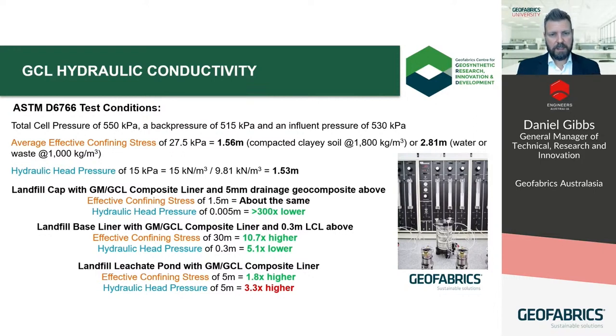liquid. So, for example, while the confining pressure may be similar in a landfill cap, if you have a relatively medium to low permeability soil in conjunction with a geocomposite drainage layer over the geomembrane and a mild slope, your hydraulic head potential is reduced to almost nothing. And your basal liners are likely to perform much better as well, given the much higher confinement and lower head pressure. A leachate pond is probably the closest you're going to get to these test values, but with more confinement, depending on the depth, but also a higher hydraulic head potential.